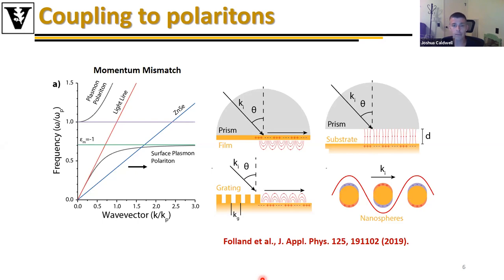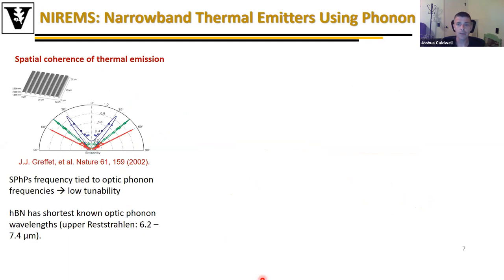Okay, so we're gonna focus first on using phonon polaritons as a means of achieving narrowband thermal emitters in the long wave IR. And this is actually motivated quite heavily by the seminal work from Professor Greffet that he highlighted last week. Just to remind you, in that case, he looked at a silicon carbide grating. This is back in 2002.